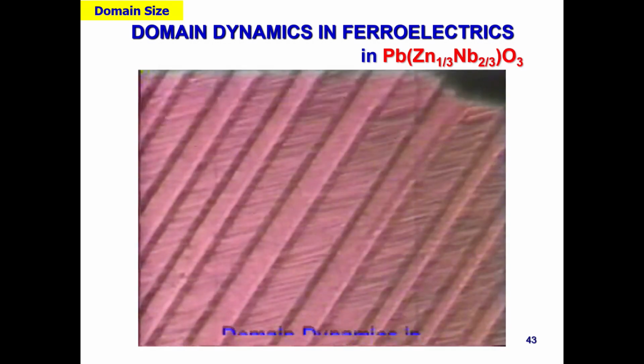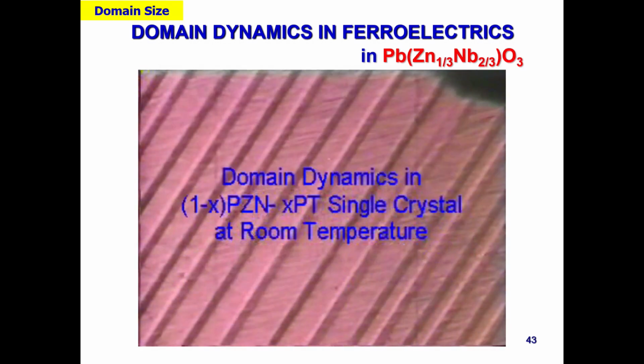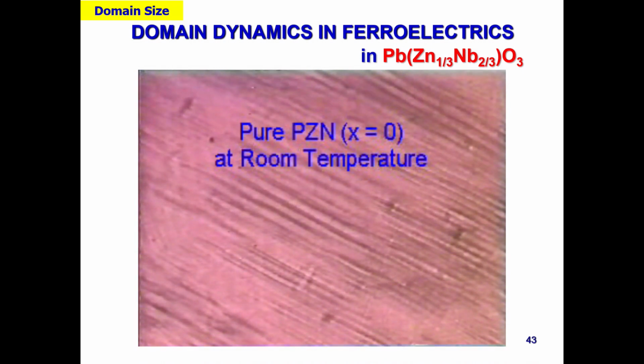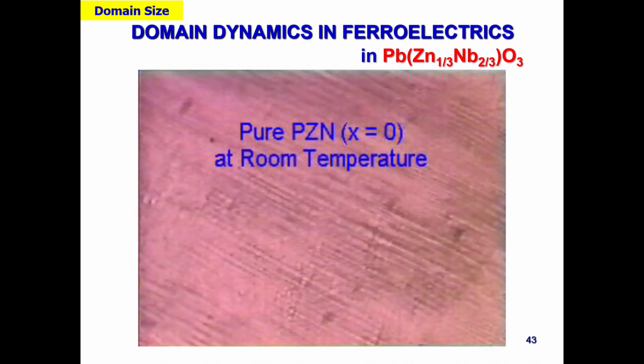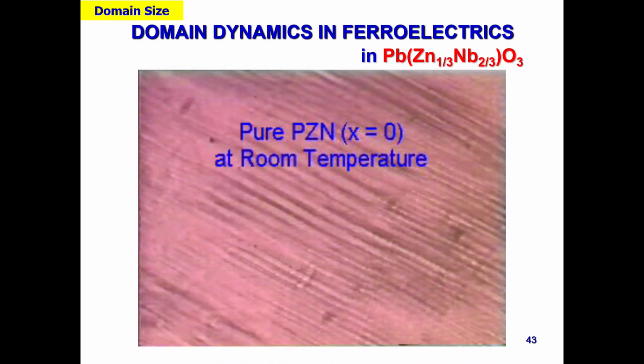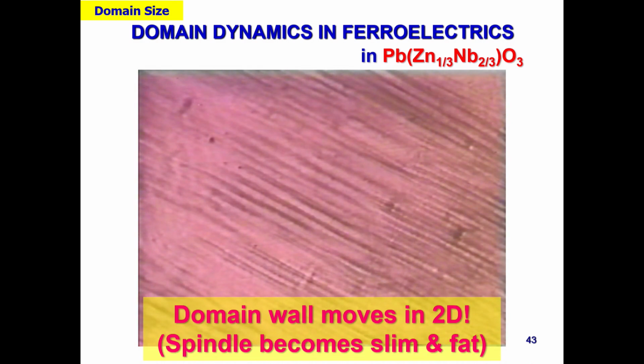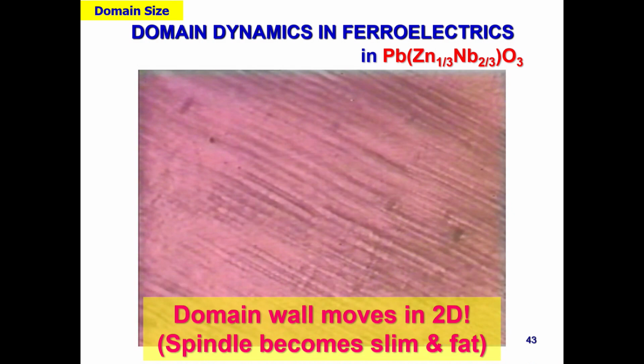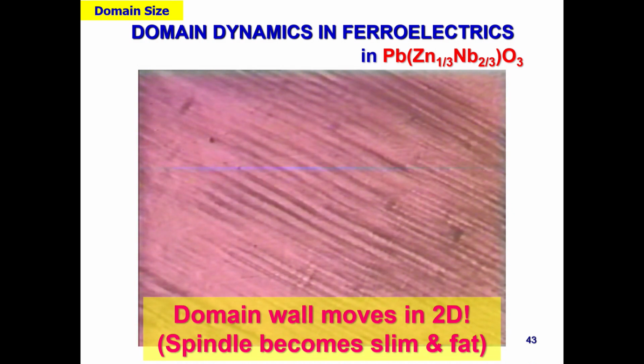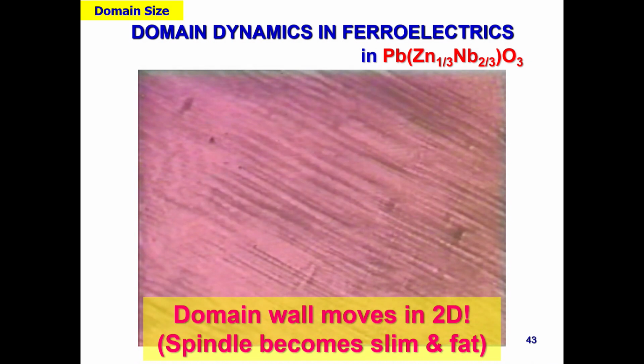Second is the PZN single crystal. And this is a pure PZN single crystal at room temperature. You can find a spindle-like domain. It doesn't become a real monodomain state. So you can find the black becomes white, white becomes black. So the domain wall moves two-dimensionally. So the spindle-like domain becomes slim or fat, moving two-dimensionally, and the length is almost constant, okay?